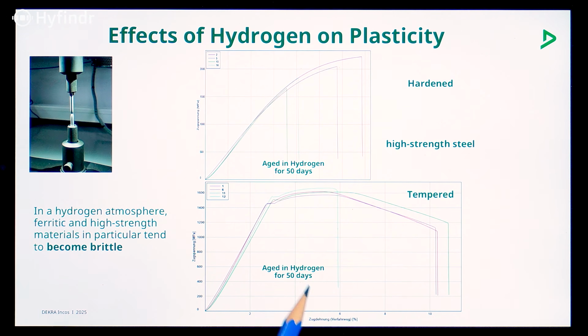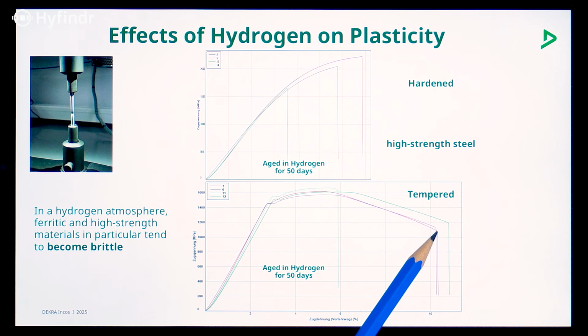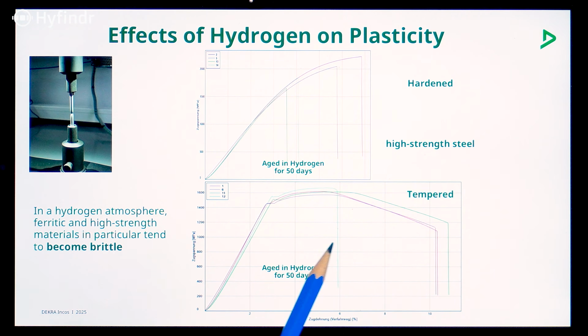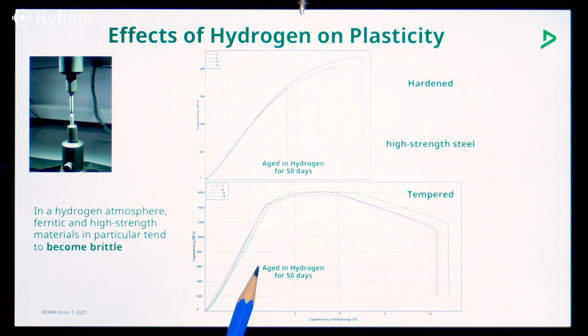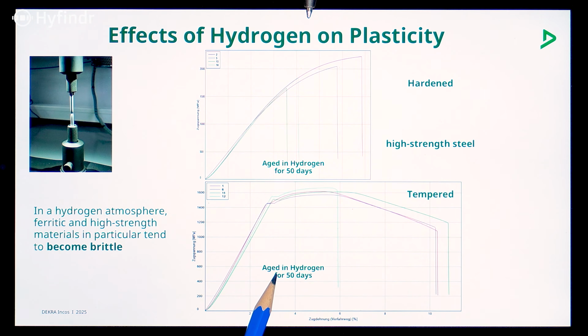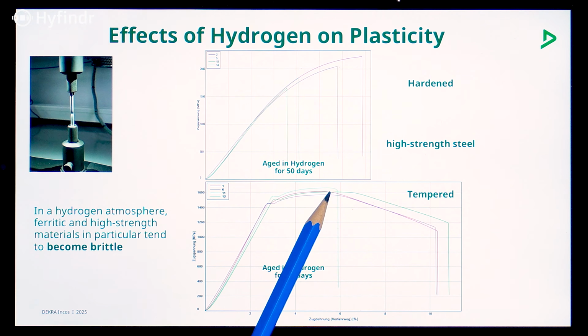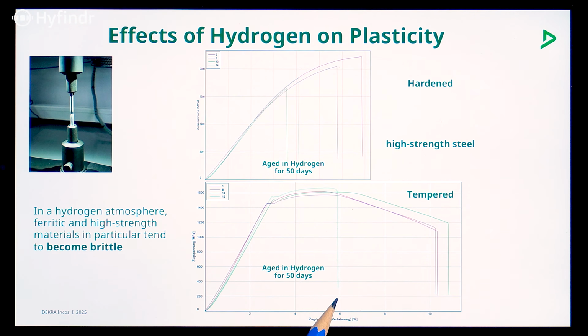But what we see here is if we aged some samples in hydrogen for 50 days, then the broken point is here. And when they are not aged, then the broken point is here. This means during the 50 days, the hydrogen went into the material, and we get an internal embrittlement. And these internal stresses reduce the ductility of the material, and therefore we get early breakage. We have nearly the same height of the tensile test, but we get an early breakage and less plasticity.